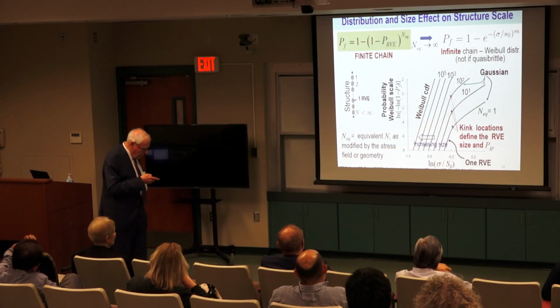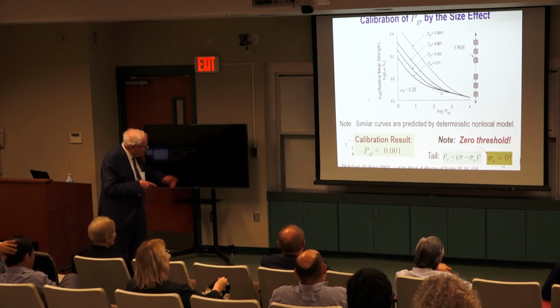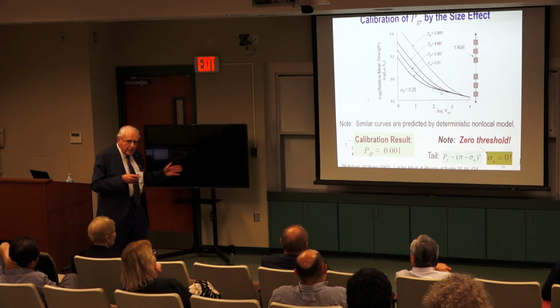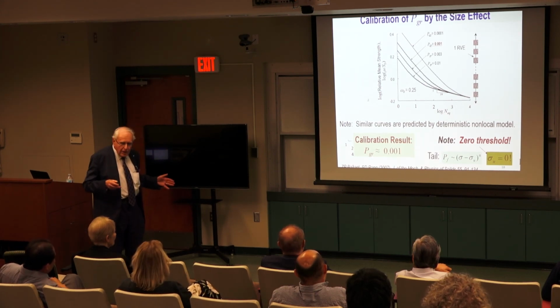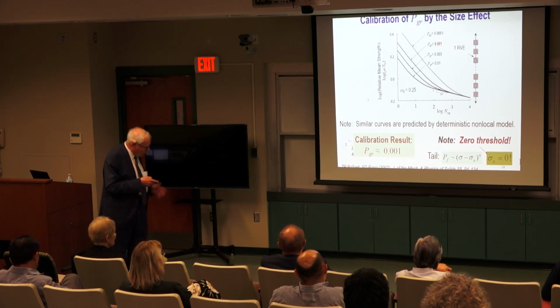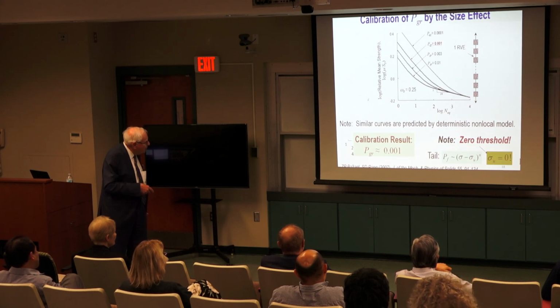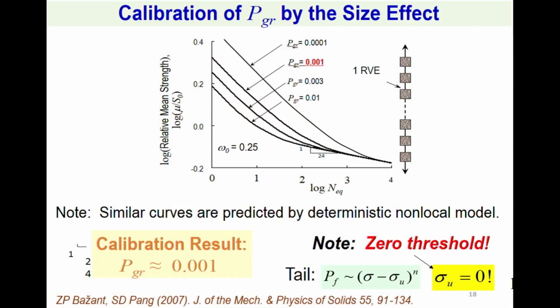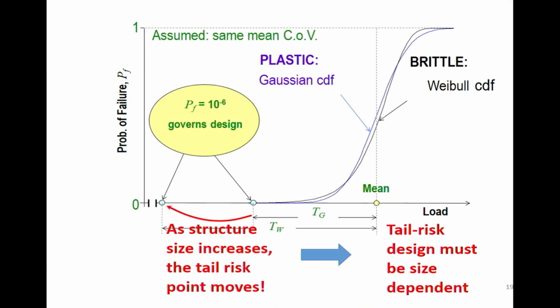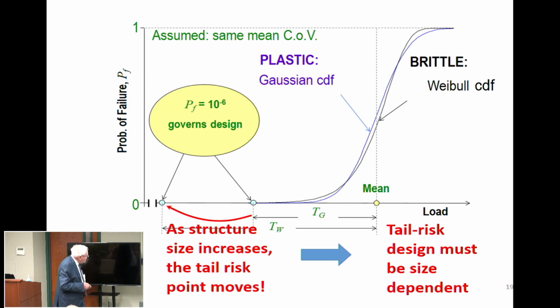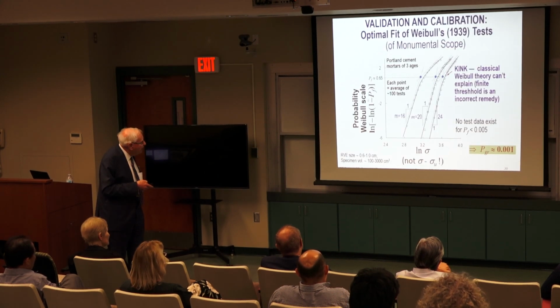In fact, you can show that if you consider a threshold and go this argument back, you will conclude that Kramers' rate and Boltzmann statistics don't apply. Then it must have a constant. It's impossible. But this is what's mainly used in the literature. So our conclusion is no threshold, and transition on the RVE scale, representative volume elements, is at about this value. We worked out a similar theory for tunneling in computer dielectrics, computer chips, then it's about 1 million. But it's a very different physics, of course. So the question is now, how do we predict changing from Gaussian distribution to this distribution on the structure scale based on what we see on the small scale.